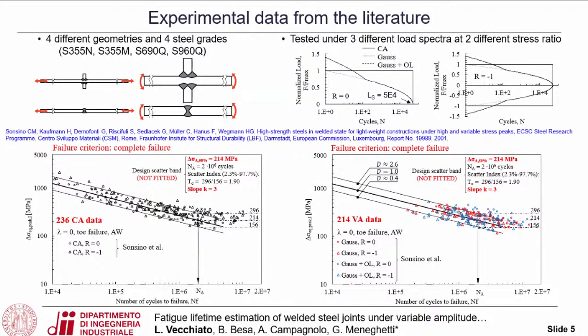The results were recomputed according to the procedure we have seen before, so according to the peak stress method, and the results are reported in the 2 charts below on the slide. On the left side are reported the constant amplitude data that are fitted on the scatter band, which is the PSM Mode 1 design scatter band, and on the right of the slide we can see the results for the variable amplitude data. We are seeing more than 200 variable amplitude data that have been reanalyzed according to the peak stress method.